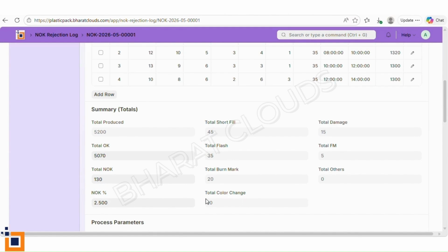Here's the breakdown. 45 pieces with short fill. That's your number one defect this shift. Short fill means the molten plastic didn't completely fill the cavity. Why? Could be low injection pressure, could be melt temperature too low, could be a blocked gate. Your quality team now knows exactly where to investigate. 35 with flash. That's excess material squeezing out at the parting line. Clamp force might be insufficient, or the mold faces might need repolishing.